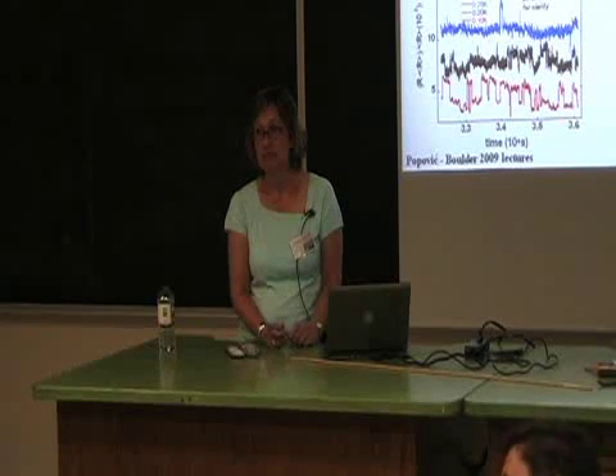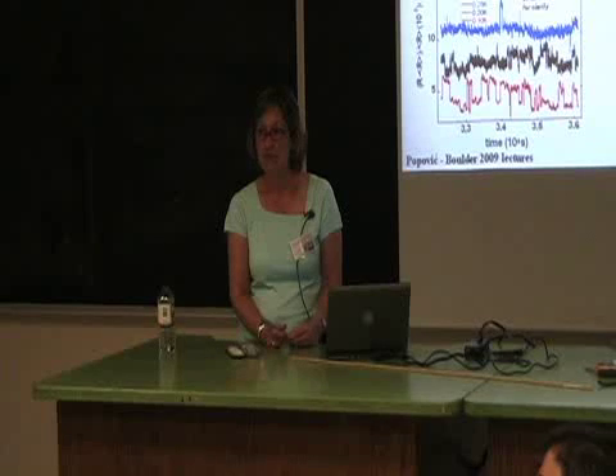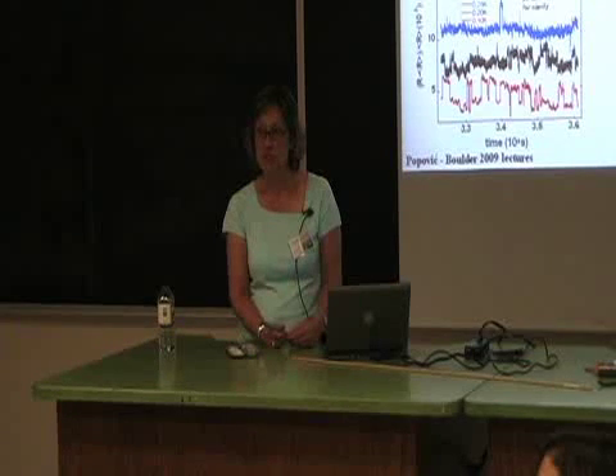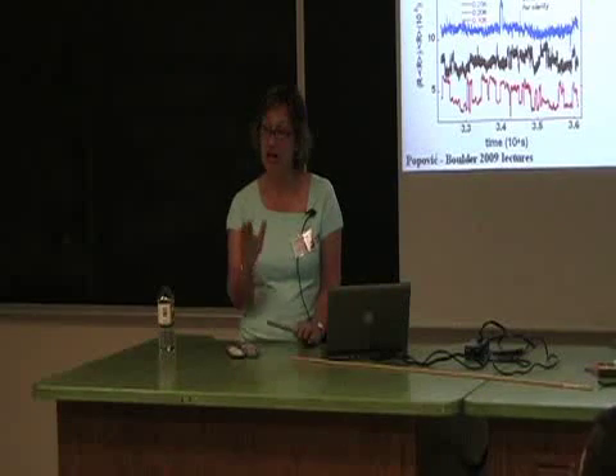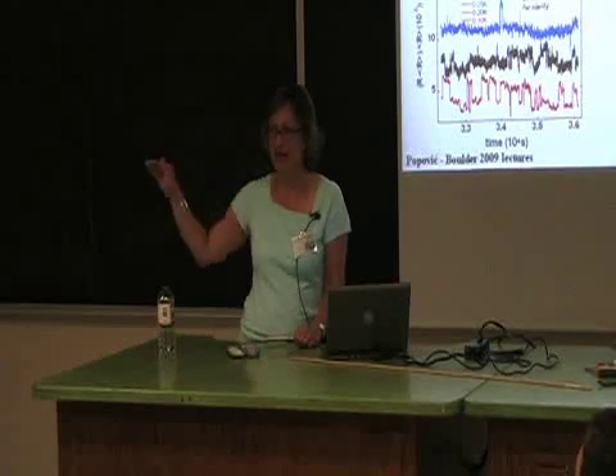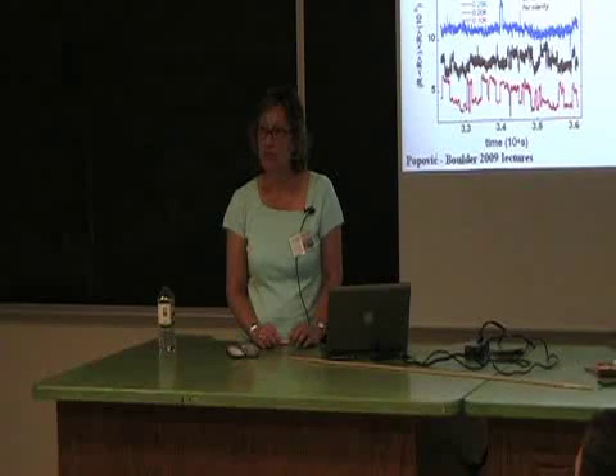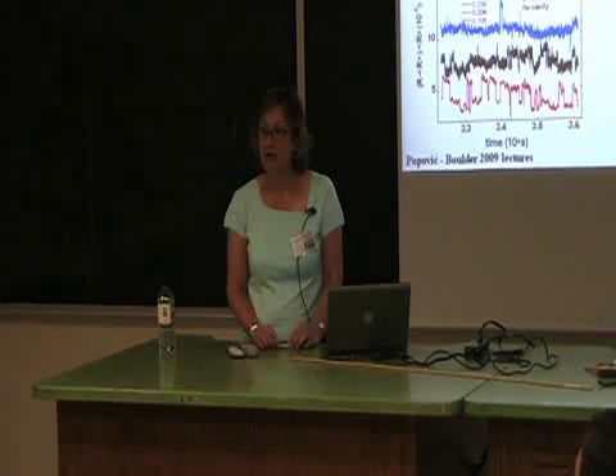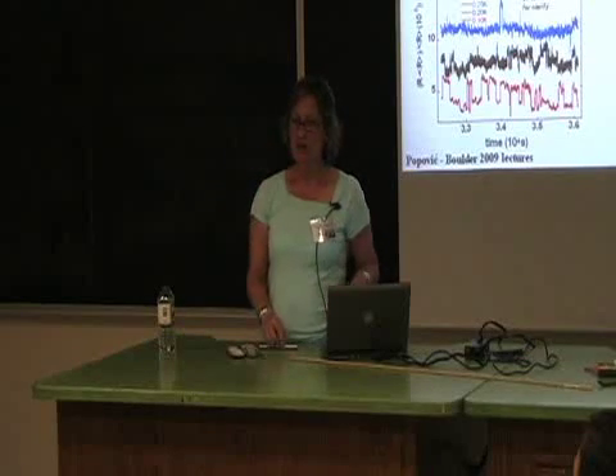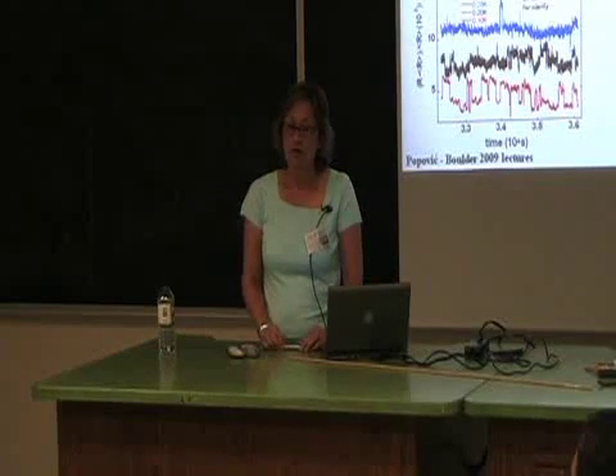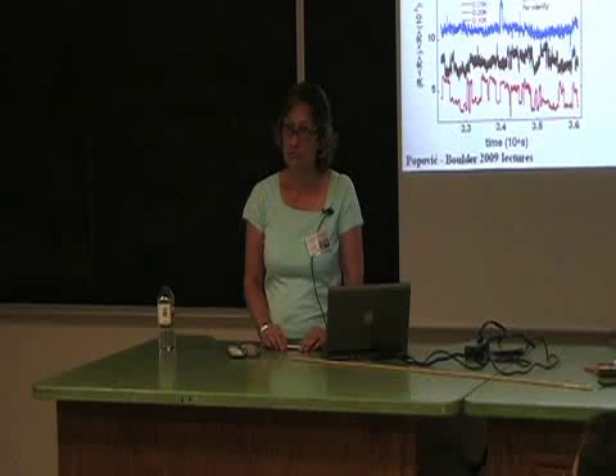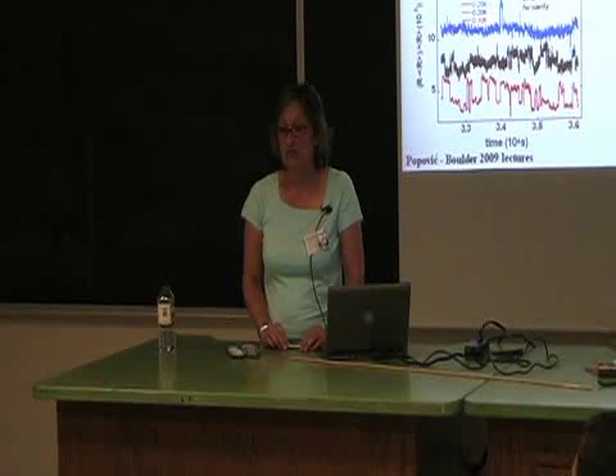So for the 2D electron gas in silicon, the glass state is due to the charge, not spin. But it seems the magnetic field still has some effect on the glass transition. Not after you fully spin polarize the 2D system. Then it's flat. For parallel magnetic field, right. It still has some effect on the transition. So is it because the magnetic field will affect the density of states or density of carriers, or still have some small orbital effect? So what do you think?